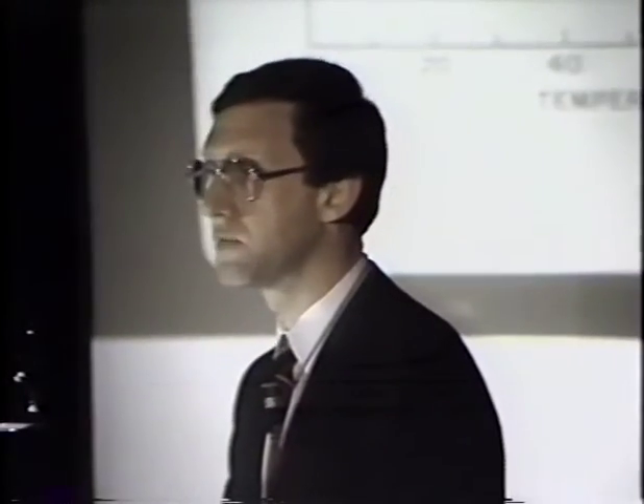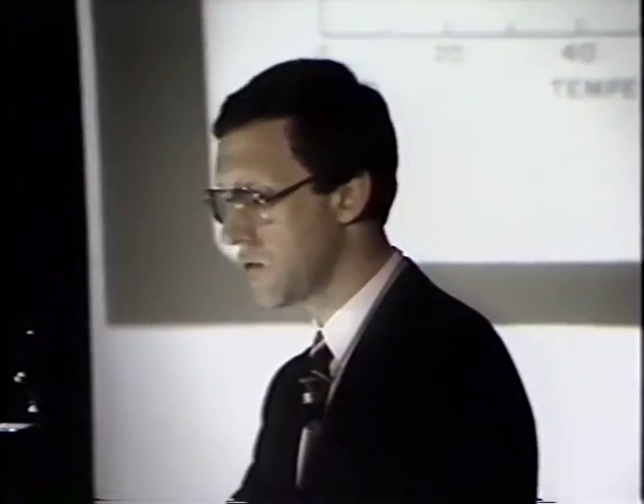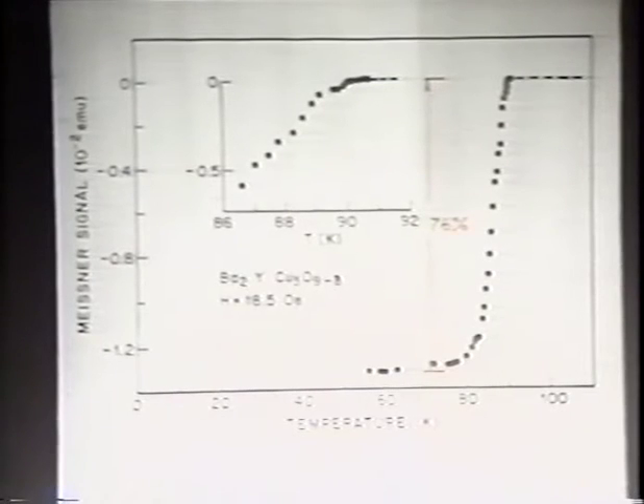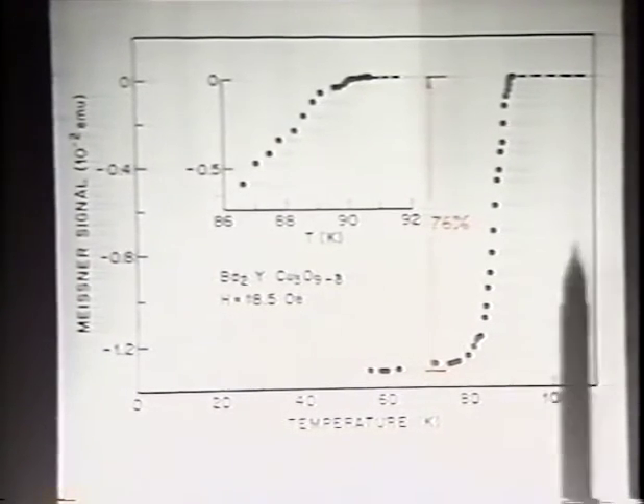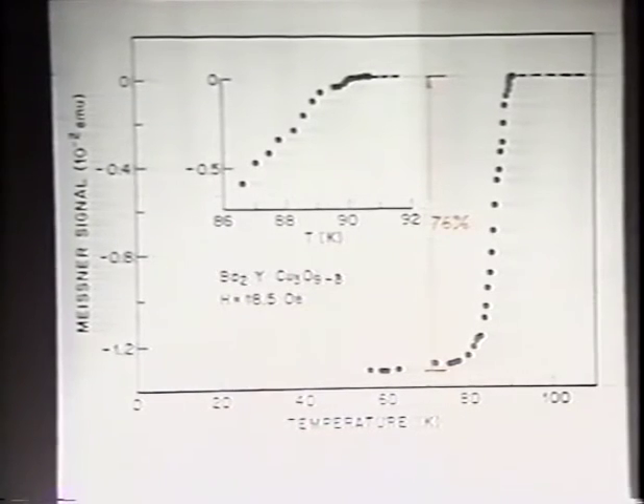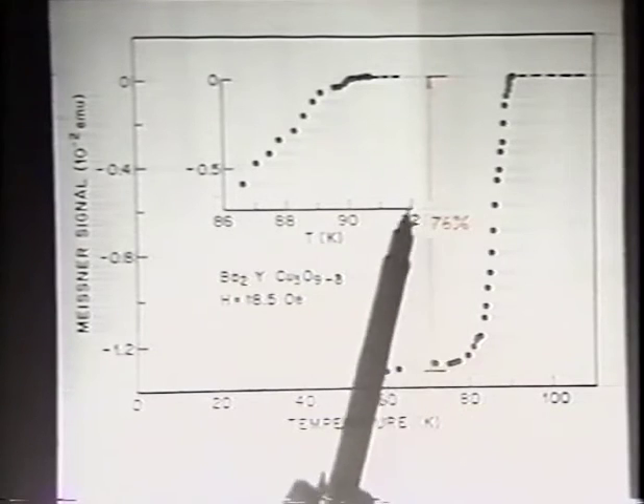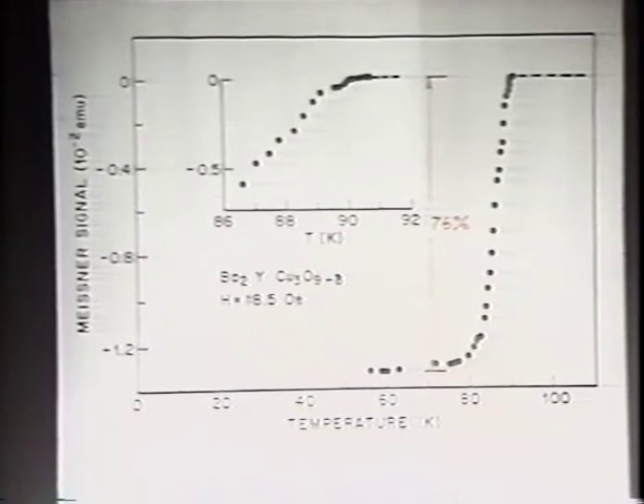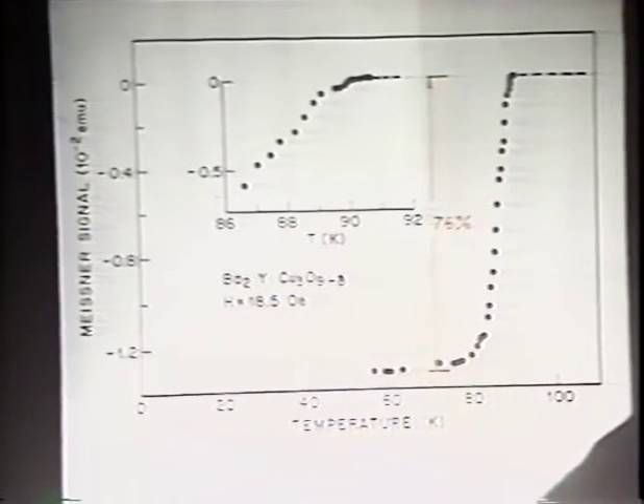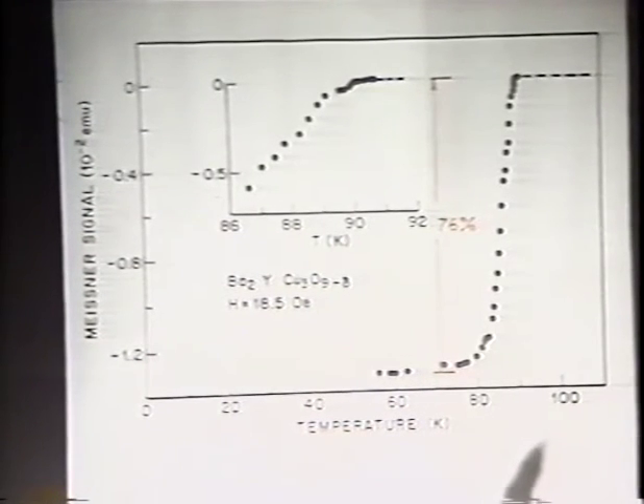One acid test for bulk superconductivity is a true Meissner effect, not to be confused with DC magnetization or AC susceptibility measurements. In an experiment like that, one cools the sample steadily in a field without moving the field, nor changing the sample position with respect to the field. What you observe is a very rapid drop at TC, and there's a Meissner signal of about 76% of the independently measured diamagnetic value. This is a very large value compared to any superconductor because one always has trapped flux in a sample.